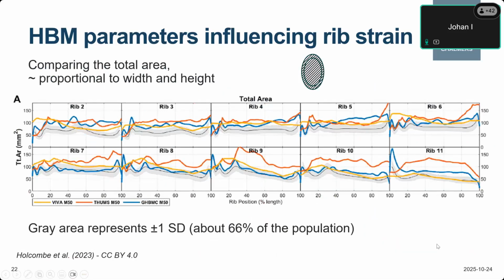So if we then start by comparing the total area, so this is the outer surface of the cortical bone, and then if we take the total area inside, what we can see, if we ignore the VIVA Plus because they are wrong, is that for the upper ribs here, the 2 to 6, the GHBMC has maybe slightly too high area for the upper ones, but then for the lower ones, it's pretty good. The THUMS model is a bit higher, so the total area is a bit bigger, and the total area is roughly proportional to the width and the height.